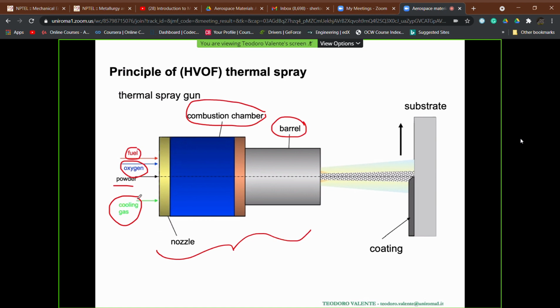For what concerns the basic mechanism, there are differences in terms of temperature and velocities, as we already have seen, but the basic mechanism of the interaction of the powders with the plume, let's call it also here in this way, is the same. That is, we have acceleration of the powders, and then melting of the powders, or partial melting, depending on powder composition. So then they are projected on the substrate to be coated. The torch, again, can be moved by using a robot, and so we can coat layer by layer also complex geometries, complex components in terms of shape.